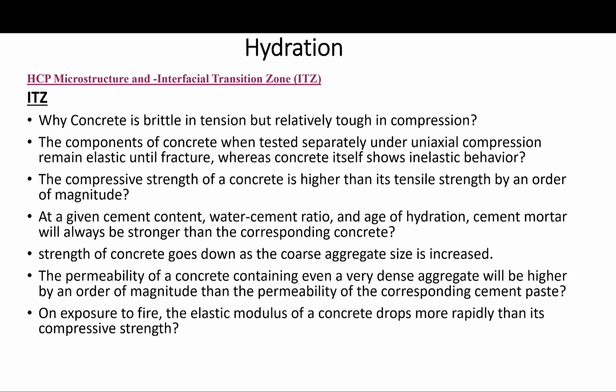Why at a given cement content, water cement ratio, and age of hydration, cement mortar, which we defined before as cement, sand, and water, will always be stronger than the corresponding concrete when we add aggregates. The strength of concrete goes down as the coarse aggregate size is increased.